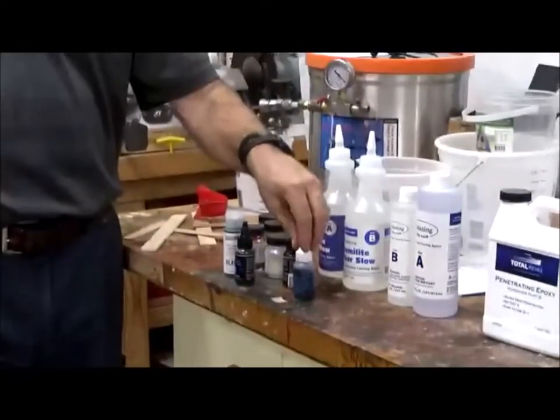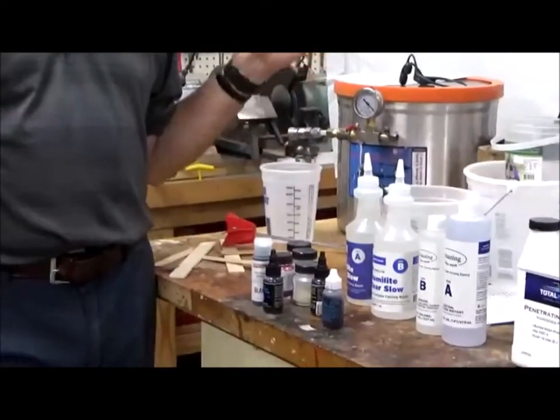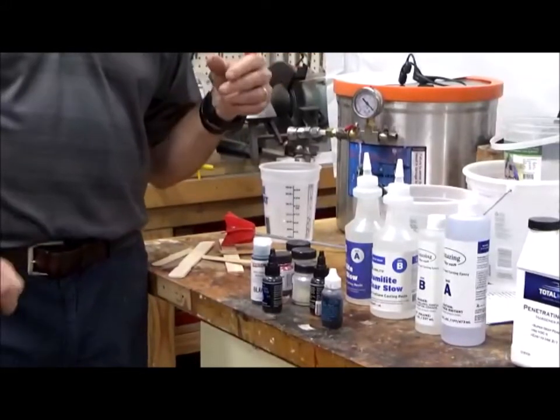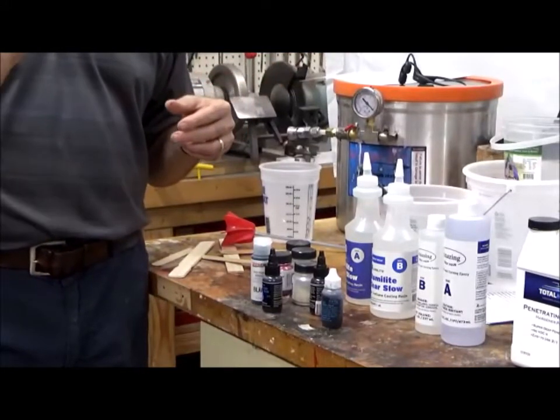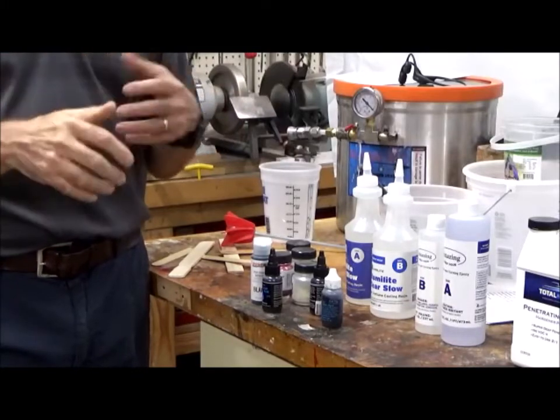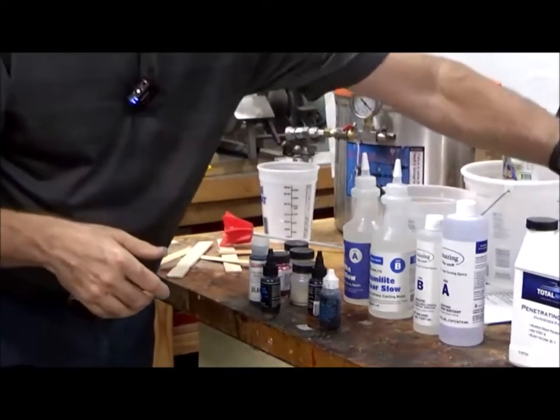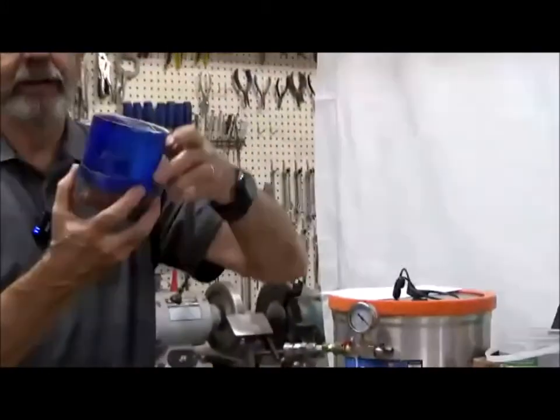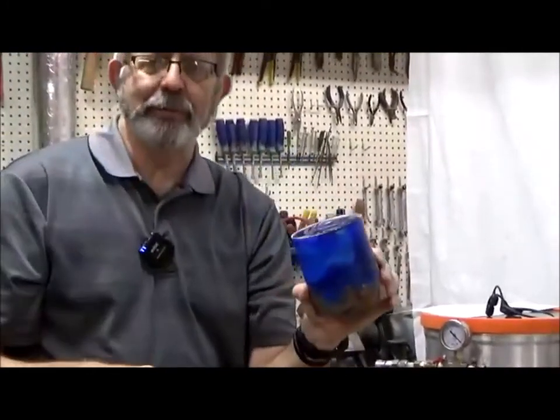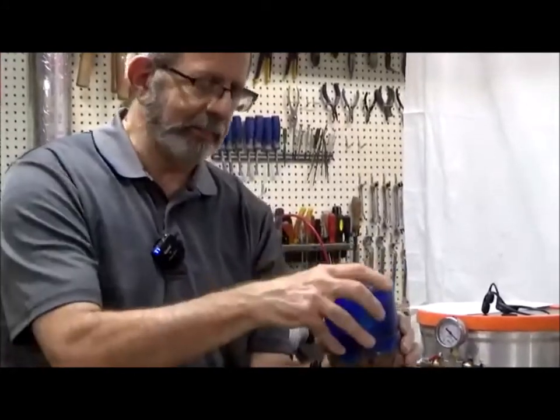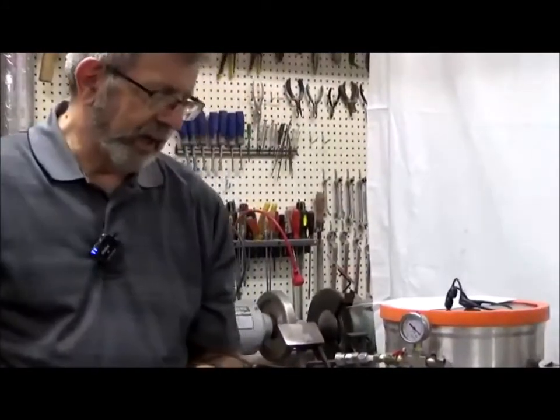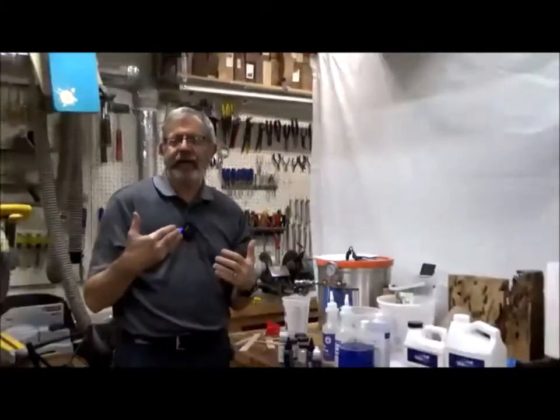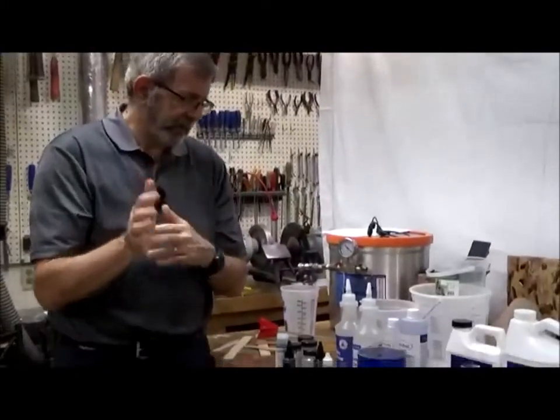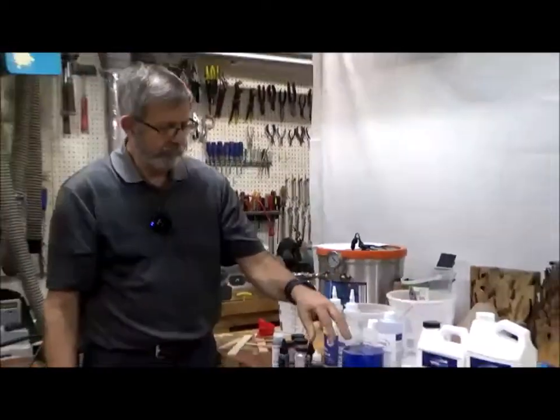This dye is very, very concentrated. I'll leave it down here so you can just zoom into these. For a 6 or 8 ounce pour, one little drop on the end of a toothpick is all that's required to dye to get a pretty deep color like this. This probably had one or two drops on the end of a toothpick to achieve that deep color. So you don't need much. If you're looking for something that's opaque, that's totally colored, then you can use more.